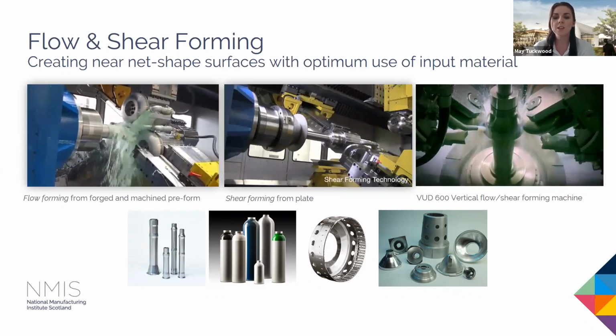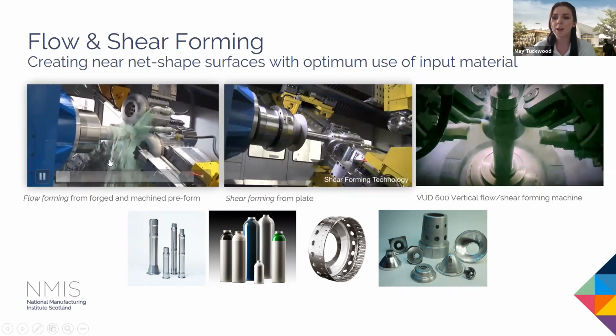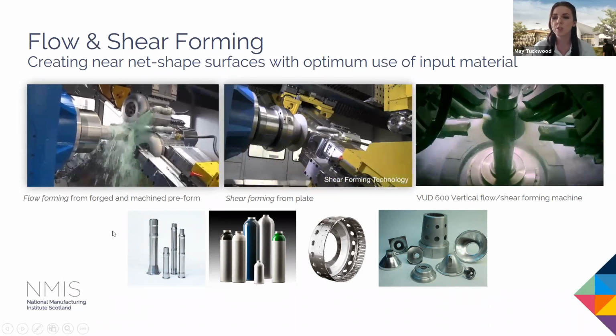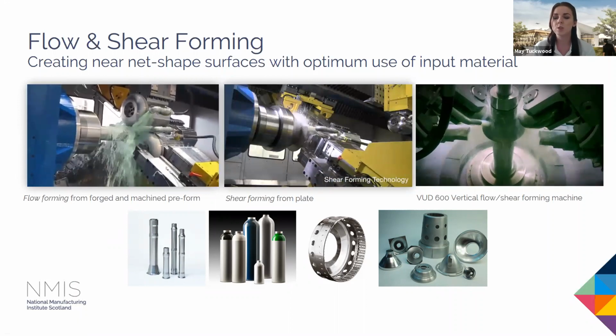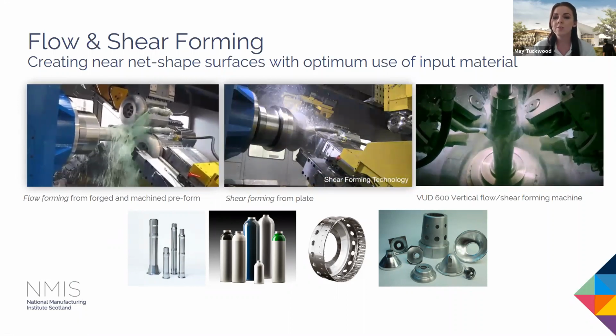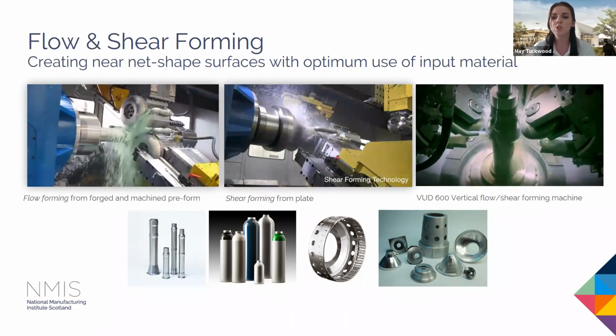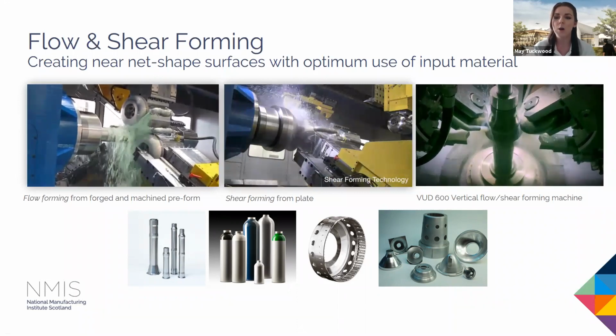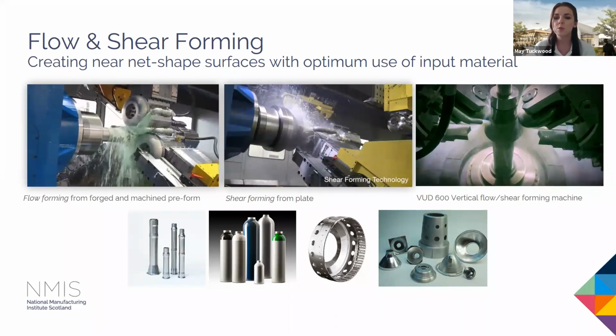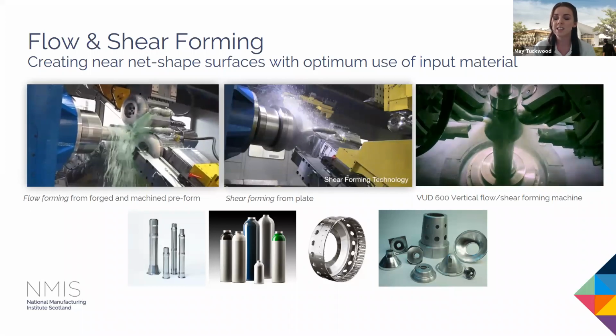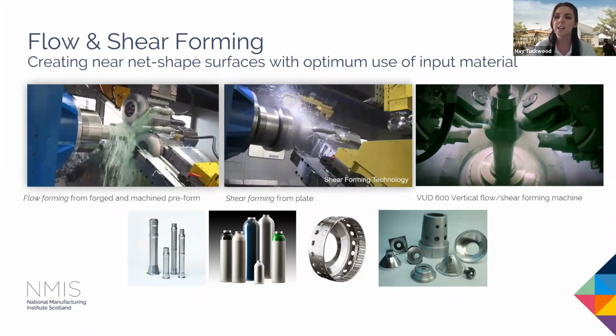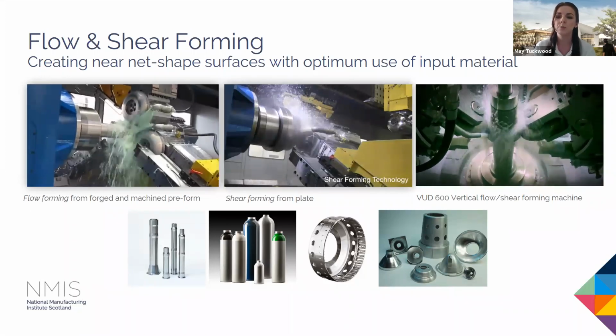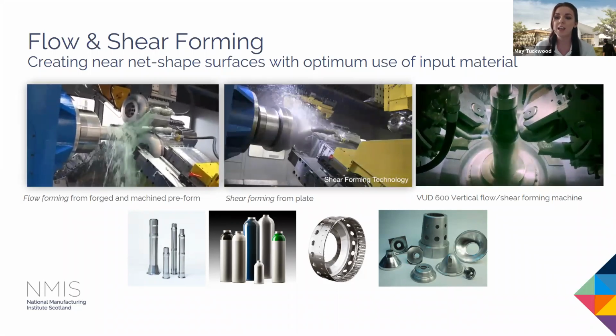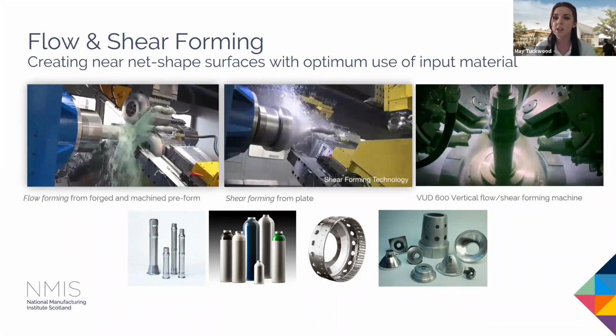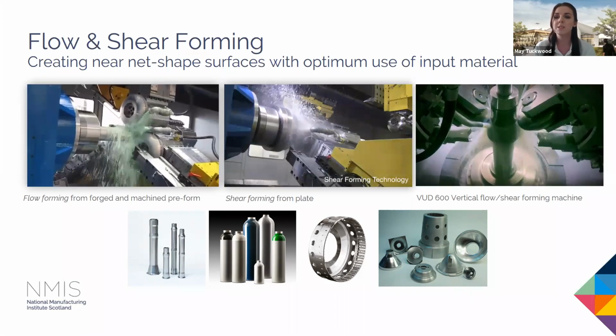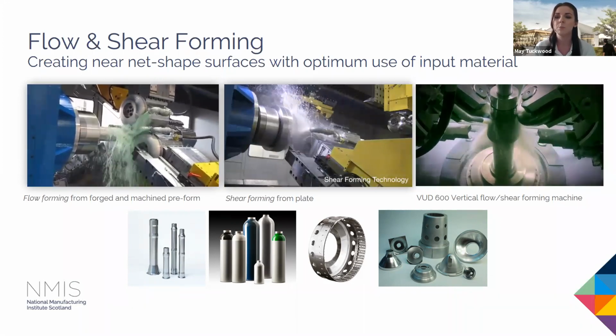So in terms of thicknesses, we're looking at reductions here between 20 and 80% of the original starting thickness, and elongation up to 200%. So conventionally, these types of components, shafts and parts like that, would be machined from solid. So the volume of material being lost is significant, sometimes 80 to 90% of the original starting material. So by forming this way, yes, we've got an element of machining in the first instance to create the preform, but the material utilisation is drastically improved.